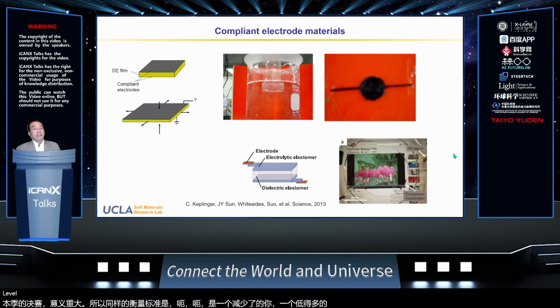They show similar actuation strength up to about 20 hertz. Above that, at 50 hertz, the film stiffens quite significantly, so the strength measured is reduced to a much lower level.